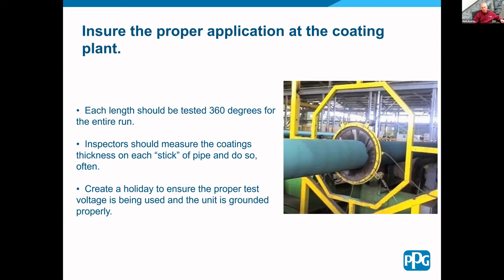The only way to ensure that you've got the proper and perfect test voltage is to actually create a holiday. So you want to find a spot, create a holiday. We use a very small drill bit, and we use our fingers to rotate that drill bit back and forth until we hit the substrate. Then we run the holiday detector towards that holiday, and we want that arc to jump twice the distance as that coating is in thickness down the hole to the substrate, the pipe, the tank, the bridge deck.